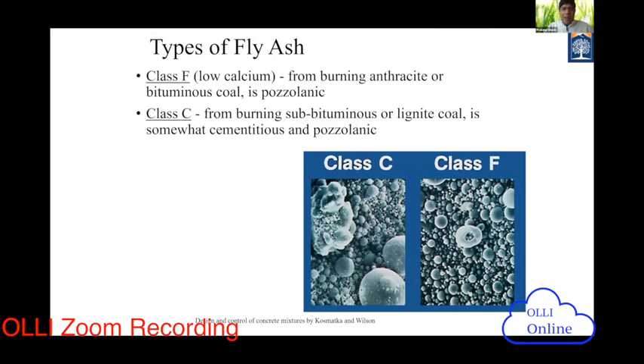We have two types of fly ash. One we call class F, which has low calcium, comes from bituminous coal, and is more pozzolanic. The other we call class C fly ash, from the burning of subbituminous or lignite coal. Different types of coals are there, and it is both cementitious and pozzolanic. Cement has cementitious properties, and pozzolans have pozzolanic properties. So we are using different types of pozzolans, but they are not the same, even within the same pozzolan, class C and class F.